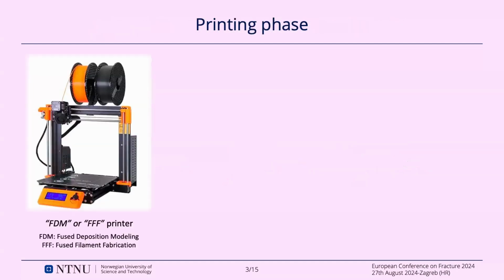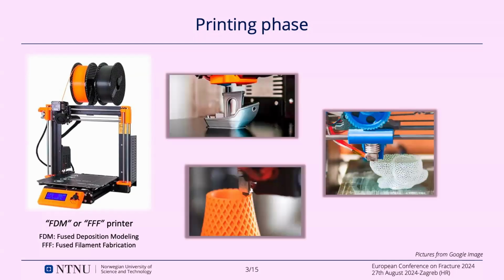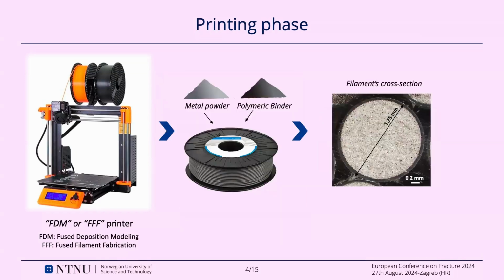The printing phase can be done with one of those printers that I assume everyone knows. So they can be used also for non-engineering purposes, and mainly the feedstock material is plastic, PLA. But we can use a special filament that contains metal powder. So it's metal powder and a polymer that serves as a binder. And you can see here a cross-section of the filament that we used. The composition is heterogeneous.